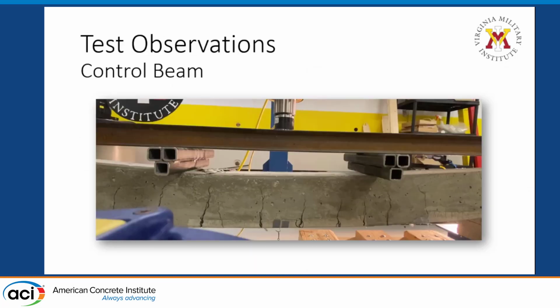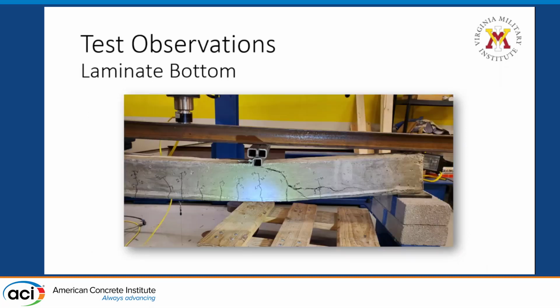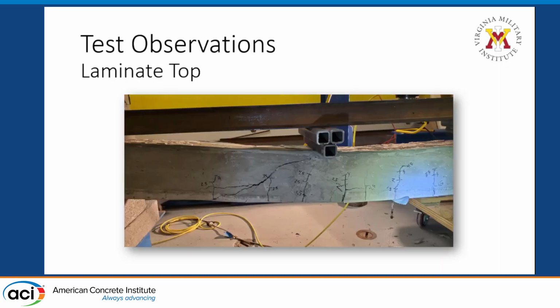Here's a picture of the control beam at failure. As you can see, it fails in tension with the middle section having the most flexure cracks. What was interesting, all the laminate beams failed in shear, and here's a picture of the laminate with it at the bottom. Shear crack on the outside section. Here's a top beam. It's the other side of the beam, but same thing here, shear crack on the outside section.